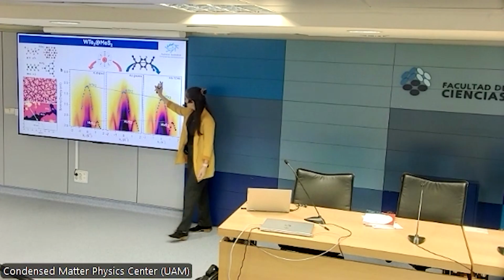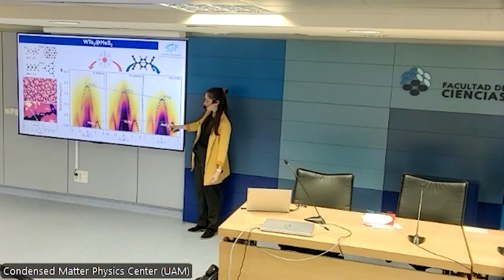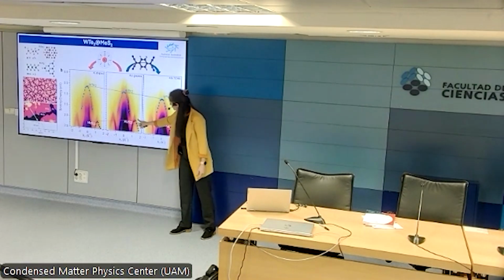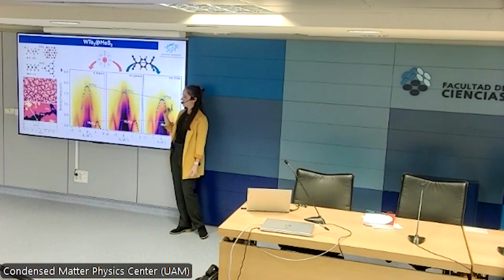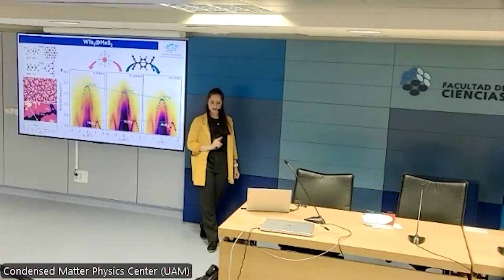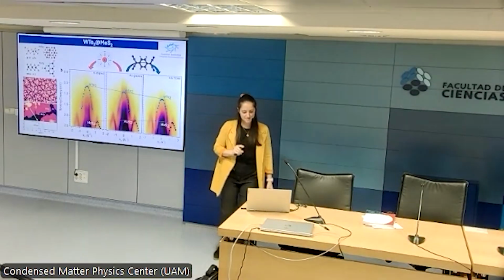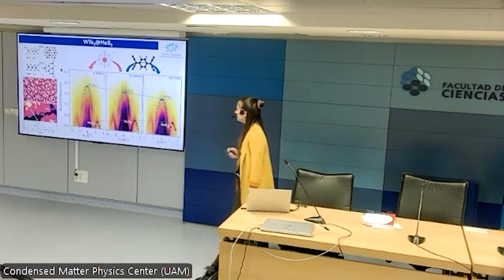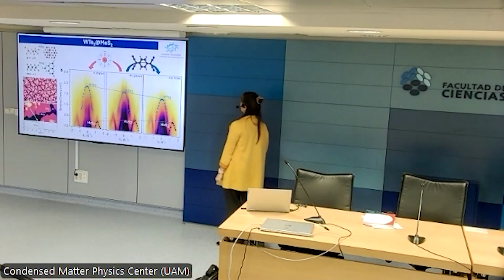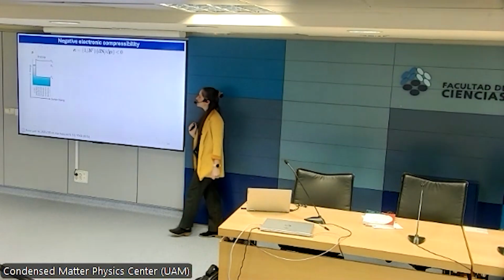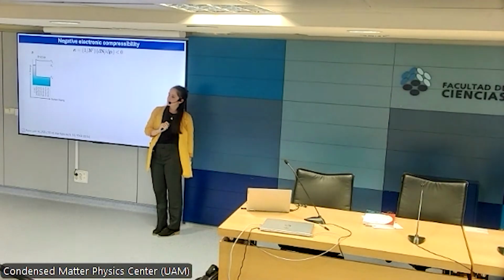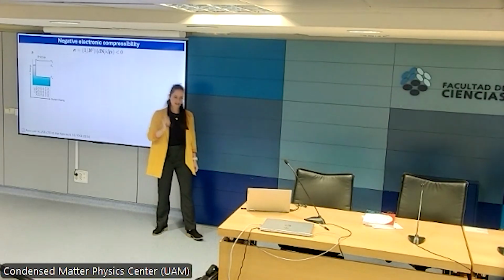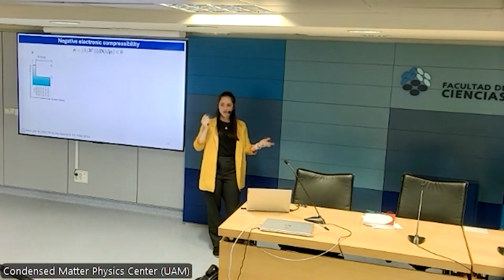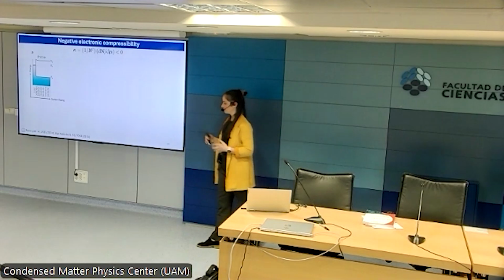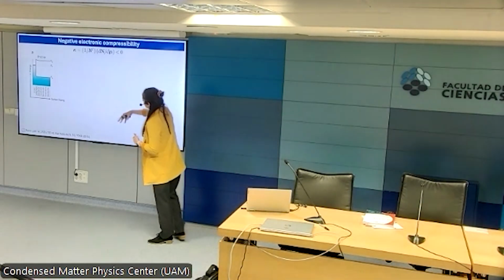But then we deposited TCNQ, and we see the opposite happen. The bands of MoS2 go upwards, and the bands of tungsten ditelluride go downwards, which didn't make any sense to us for a very long time. We scratched our heads a bit until we found two papers about the fact that monolayer TMDs can exhibit negative electronic compressibility.